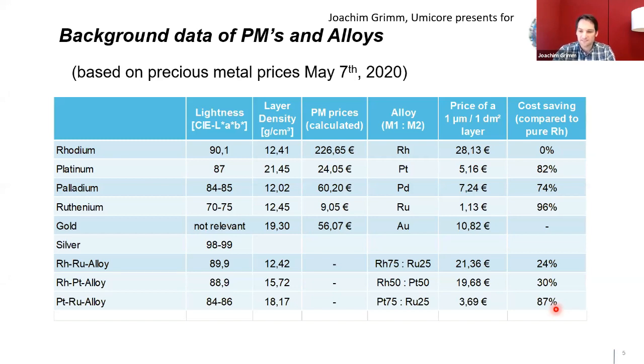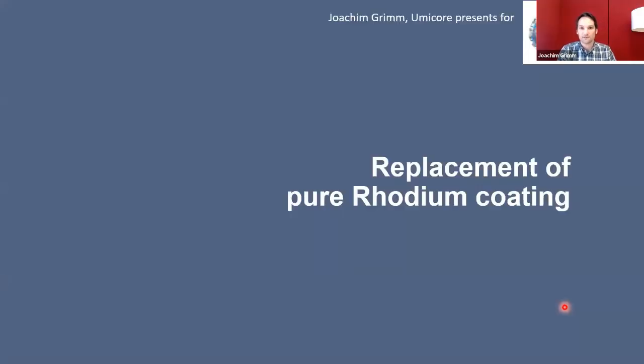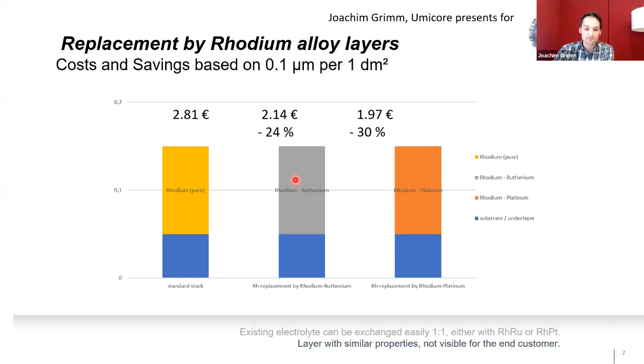So how can this be handled in the plating actually? If you want to have a layer sequence, how to do that? So how to replace the rhodium coating, the pure one? So we got the numbers again. In this case, I took not 1 micron on a square dm. I took a more standard plating layer of rhodium, 0.1 micron on a jewelry piece. Let us say our standard stack could be sterling silver plated by pure rhodium. Comes to a pricing of €2.81 in the standard stack. This is what usually the jewelry market is selling you, or you manufacture and give it to the market.